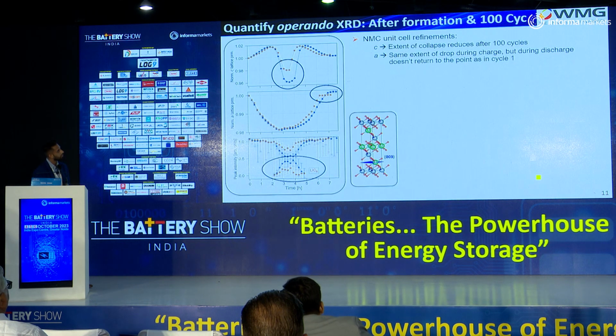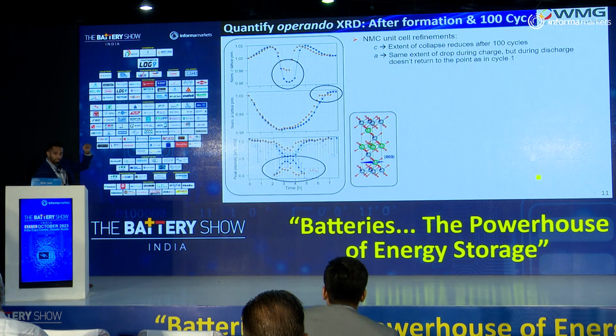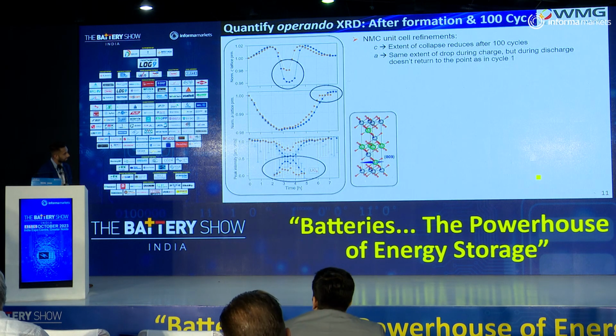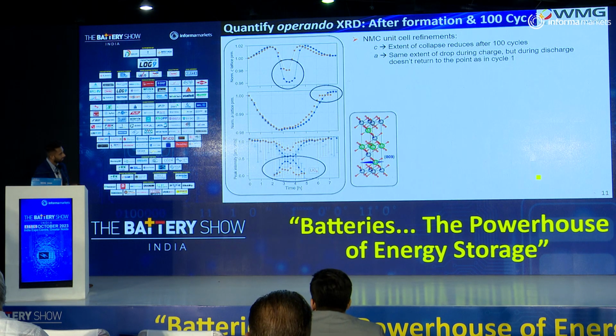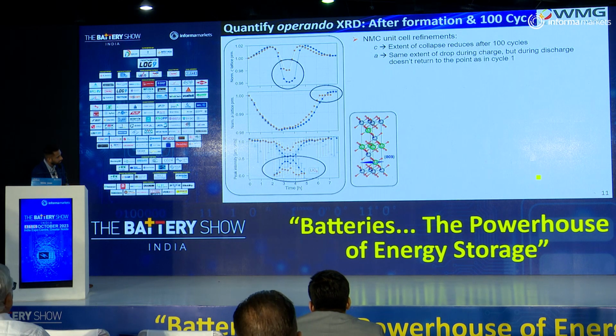Now, I mentioned that we can do atomic level understanding, and I explained that we get our expansion and contraction of our material, so that's in the 003 plane. And our lithium sits here, our transition metal layers sit here, so our nickel, manganese, cobalt, and our oxygens are highlighted in the red. NMC materials and transition metal layered oxides have a very big problem with oxygen loss.